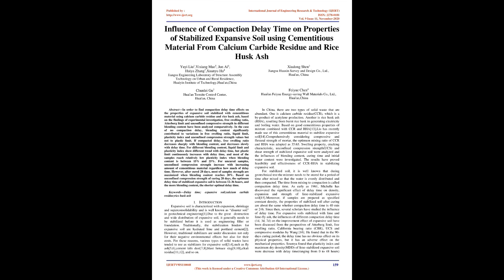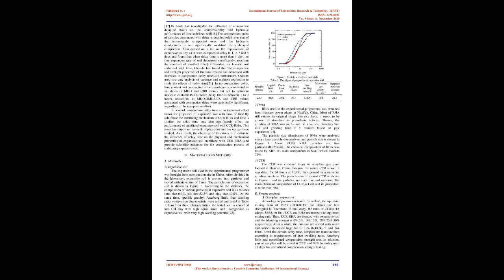Since then, several scholars have studied the influence of delay time. For expansive soil stabilized with lime and lime fly ash, the influences of different compaction delay times, 1D, 3D, 7D, on the improvement effect of expansive soil have been discussed from the perspectives of Atterberg limit, free swelling ratio, California bearing ratio, CBR, UCS, and compressive modulus by Wang 16. He found that in the 90 days curing period, the delay time has no obvious effect on its physical properties, but it has an adverse effect on the mechanical properties.